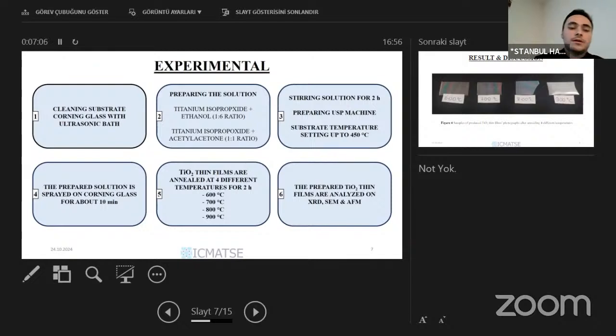After we obtain the thin films, we need annealing for a better structure and better properties. We use 4 different temperatures: 600, 700, 800, and 900 degrees. All samples are annealed at these temperatures for 2 hours.